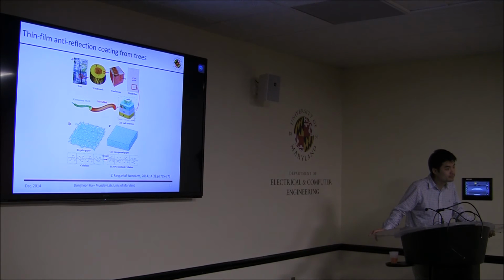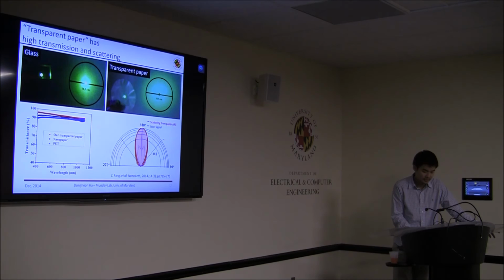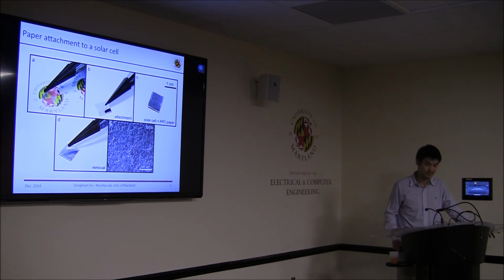I also have a question. Because you use paper as the anti-reflection coating on the surface of the solar cell, how do you make sure that this paper will stick to the surface of the solar cell? Okay, that's a really good question. So actually the attachment process was really tough at the initial stage of my research, because I have the paper, I have the solar cell, I need to attach it, right? But I had a hard time attaching the papers to actual solar cells, because if we have air gaps, what you want is a gradual index change from the air to the solar cell, because the refractive index of the paper is somewhere between those two. However, if we have some air gaps, that's going to break the whole thing.